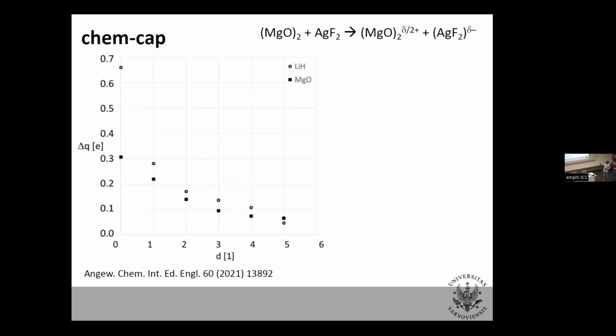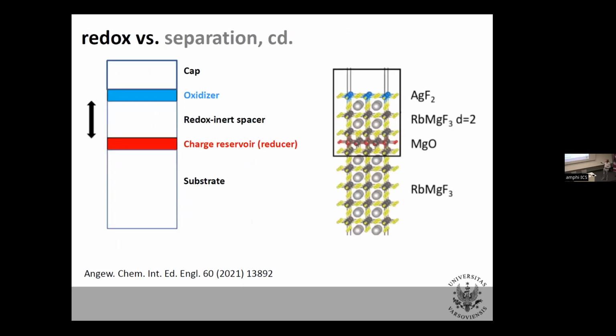Here, I didn't change stoichiometry of these layers of oxidizer and reducing agent at all. I didn't permit any contact. When lithium enters CoO2, it enters the structure, travels through the structure, sits there, and this is how it dopes. I didn't do that here. My layer is here, that one is here. They do not move. And yet they dope each other. They dope mutually each other. So one dopes the other and the other dopes this one. So one is doped with electrons and another is doped with the same number of holes.